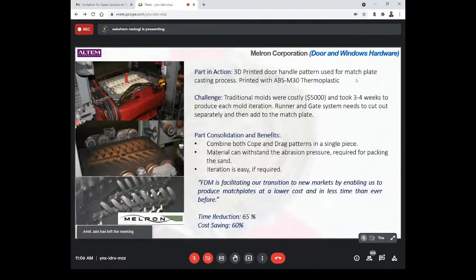So this is one example from the Melron Corporation for the manufacturing of door and window hardware. You can see in the photos the 3D printed pattern in white color, the next photo is the cavity mold for the sand casting, and the third photo is the manufactured parts with the sand casting solution. The challenge was the additional cost, which was around $5,000 or more, and it took around 3 to 4 weeks for the mold iterations, and also to make the runner and gate system, which needs to be cut out separately for the sand casting solution, and then add the match plate.